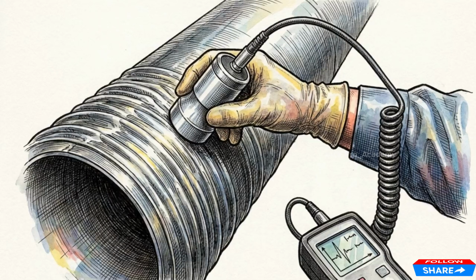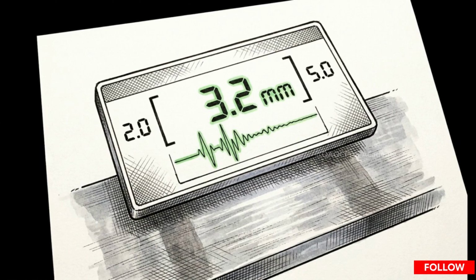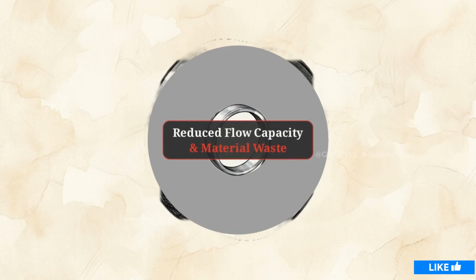Use an ultrasonic thickness gauge to map the exact depth of the cooled weld overlay. Your compliance window is narrow. The overlay must measure uniformly between 2 mm and 5 mm to meet industry standards. A layer thinner than 2 mm will eventually corrode, while exceeding 5 mm wastes an expensive amount of raw Inconel.